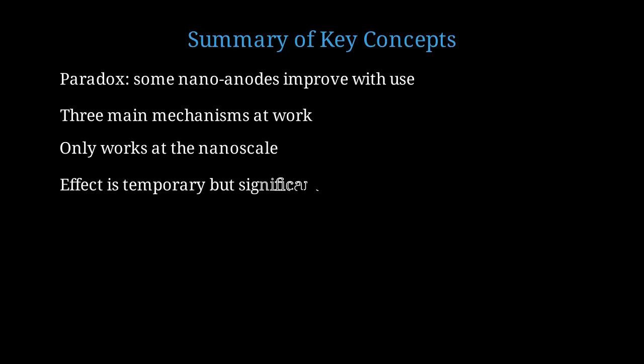Let's summarize the key concepts we've covered. The Nano Battery Lifetime Paradox is that some nanostructured anodes actually improve with cycling rather than degrading. 3 main mechanisms drive this: particle reshaping that increases surface area, interface stabilization that reduces resistance, and activation of hidden storage sites. This phenomenon only occurs at the nanoscale, typically for particles below 100 nanometers, because that's where beneficial restructuring outweighs catastrophic failure. The effect is temporary, lasting for tens to hundreds of cycles, but the capacity gains can be 20 to 50%, which is significant.